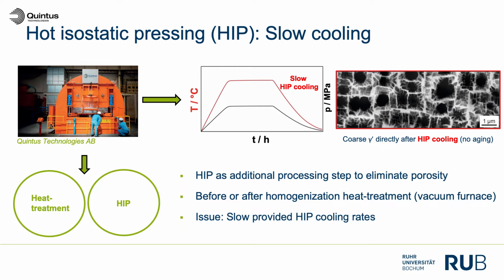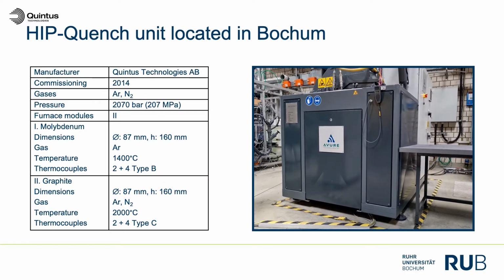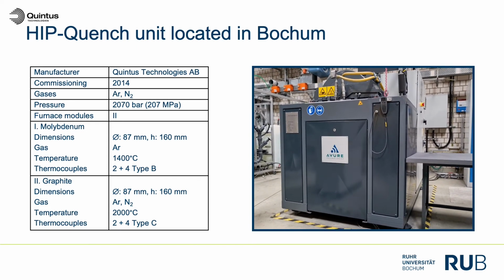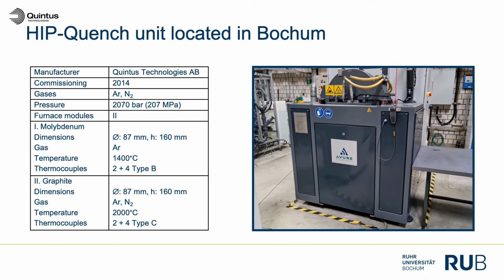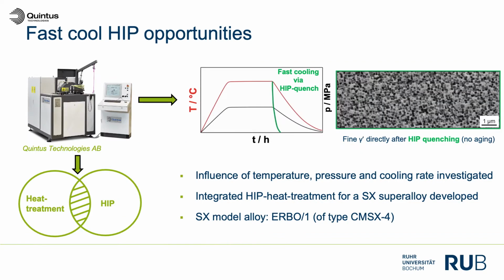Here we saw a lot of problems in the past and looked for a solution. Then we did a little research and found that Quintus has a new technology with this fast cool capability. So we decided to buy a small lab scale HIP unit, this QIH9 model with ultra rapid cooling capability. This brought up many new possibilities for us. We found a lot of research that had never been done in the past, and then we started to look at the influence of all the parameters that we have during the HIP heat treatment.